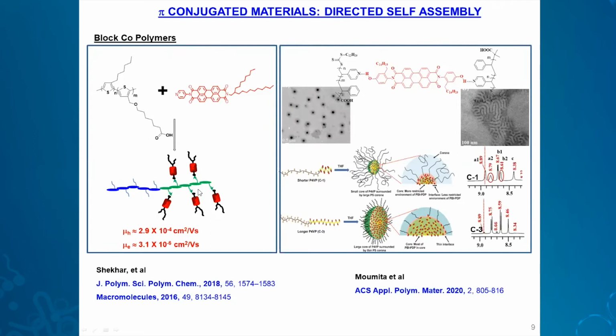Hole transportability comes from the backbone, which is the donor polymer, and the electron mobility comes from this small molecule, which is self-assembled. This is some recent work where we made the block polymer of polystyrene and P4VP. The block polymer itself self-assembles into this beautiful morphology. But when you add the small molecule, which can selectively self-assemble only with the P4VP unit of this block polymer, the same morphology is modified into this type of structure.